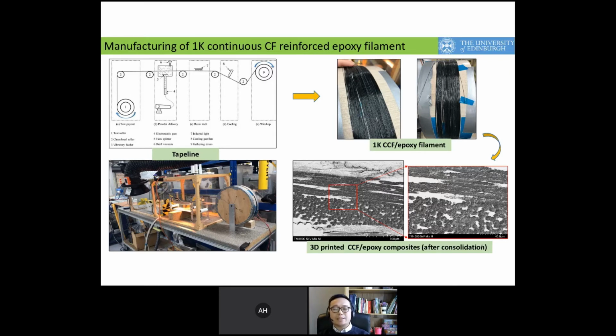We then tested the filament for 3D printing of UD laminae and laminates. We found that after consolidation, there is very good wettability and bonding, and there are no noticeable voids present. The fiber volume fraction in the filament can be easily controlled by adjusting the electrostatic powder deposition process. Up to 60% fiber volume fraction can be achieved, and that gives us the flexibility to produce bespoke filament for specific applications.